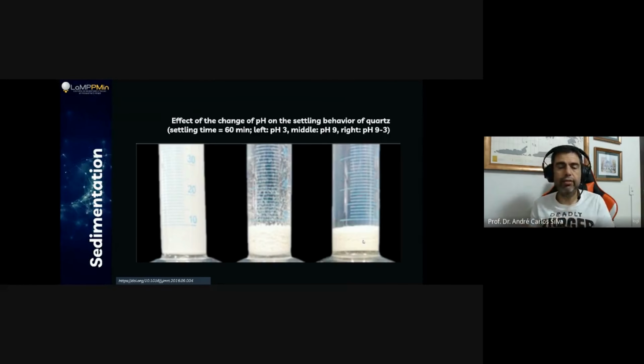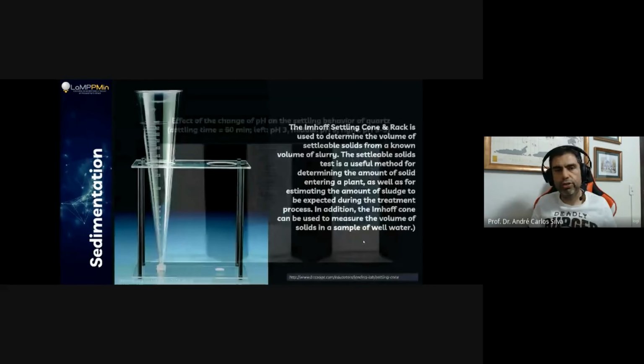Okay, and as you can see, for the cylinder in the middle, if you take a look, pH 9 is the better one. From these two pH, pH 9 is better. But how about I start the process at pH 9 and then switch to pH 3? You're just going to freeze your material at a certain pH, and you can't just convert pH from one side to the other without taking into consideration what's going to happen with your material. Okay, and that's what this picture is showing you.